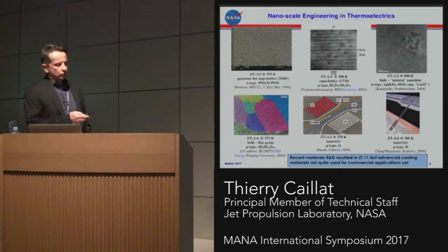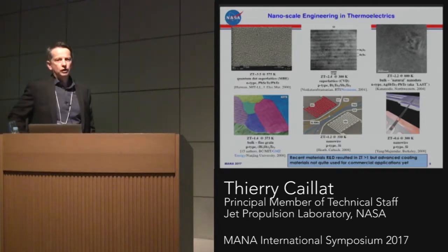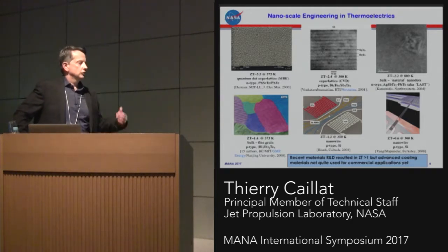There has also been some work, mostly in the cooling area, which may be more applicable in terms of nanostructuring, and you can do this with lower dimensionality or superlattices. That's the one I mentioned about the ZT of bismuth telluride. There are all kinds of things, mostly around room temperature, and these are potentially much more applicable to make it into an actual device, because you don't suffer from the grain growth that I just mentioned. Although these were reported almost 17 years ago, none of those advances in materials have made it yet into an actual device. Beyond the material itself, there are a lot of system integration and device integration issues that need to be resolved, in terms of compatibility with the heat fluxes and everything, that are still pretty challenging to solve.